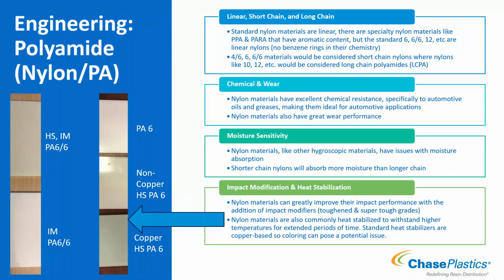The one thing I like to point out is that standard heat stabilizers for nylon are copper based, and copper tends to make the material a little more green in coloring. So if you're color matching something and using a non-copper heat stabilized material, then switch to a copper heat stabilized material, you're going to see a variance in color - it's going to look different. Or if you want a very specific color every time, you're going to have variation in the green hue of each lot, so you have to fight that as well.